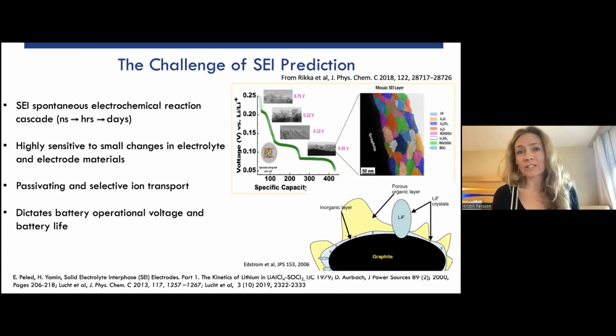From a modeling perspective, that's highly challenging, because most of our accurate modeling techniques do not extend to those kinds of timelines. We also know that it's highly sensitive to small changes in the electrolyte and the electrode materials. You add a little methyl group to one of your solvents and suddenly you have a completely different SEI with different properties. We desire it to have very specific functionality, even though we have very little control of how it forms. We want it to be electronically passivating, thin, and exhibit selective ion transport. So we want the working ion to go through, preferably as fast as possible, but nothing else. If the anion goes through, then we usually wreak havoc on the electrode material, your anode. And this SEI, despite our lack of control, dictates battery operational voltage as well as life. So it's a very, very important problem.